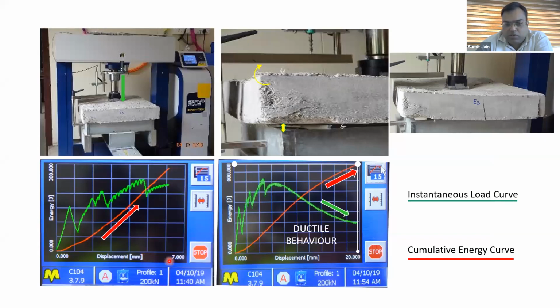Up to a displacement of 7 mm, things are moving on very well. We have 2-3 ups and downs. Now as we have reached 20 mm, here you can see the panels are getting uplifted. All 4 corners of the panel uplift because the cracks have started forming, and you can see the panel has left the apparatus. This graph corresponds to this image. We can see a ductile behavior because this panel has fibers in it, and the energy is gradually increasing.